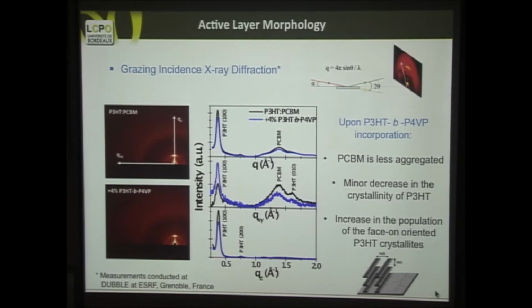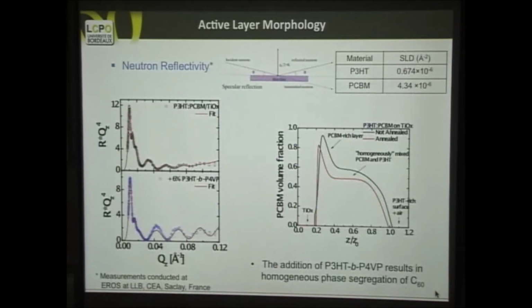Now, when you put this block of polymer, instead of the crystals going down with respect to the electrode, face on, we say, they go edge on. This is apparently what happens as you cast the pure blend. When you put the copolymer, they go face on. And you can understand that when it's face on, then the charges that you will create on this conjugated material will come out from the electrode much easier than when they are edge on. And you see, this is what we found out, that we increase the face on configuration with respect to the edge on configuration. All right? This is what you want to do, and you can engineer it. But this is not the end of it.